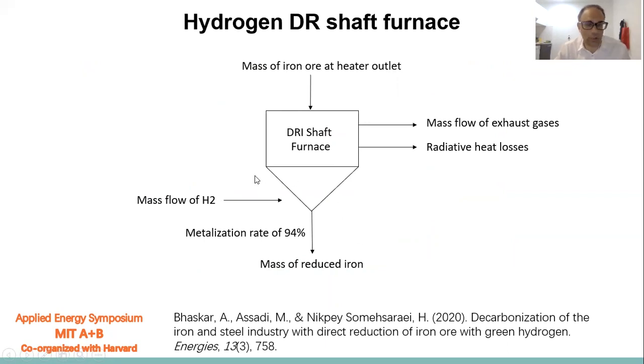These are the mass flow of the direct reduction process, which maybe is the most interesting. And we see that it is performed in a furnace in which iron and hydrogen are in counter current. And the metallization rate of iron is 94%. This means that the metal iron which exits the reactor is about 94% of the metal that entered the reactor. The mass flow of exhaust gases is represented by unreacted hydrogen and steam.